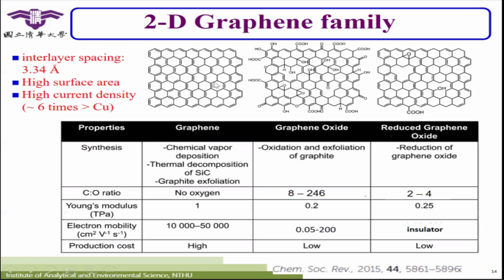Left with no functional groups on the surface, their conductivity is good. You can see their electron mobility is quite high. But this material cannot be dissolved in water. They can only dissolve in solvent. It is not as easy to use in our daily life. So people would like to oxidize them into graphene oxide.